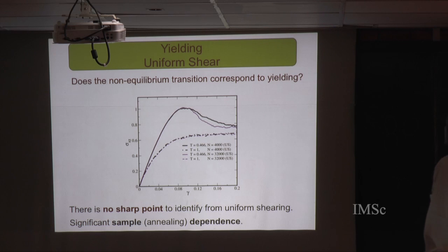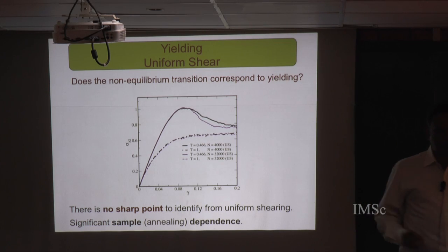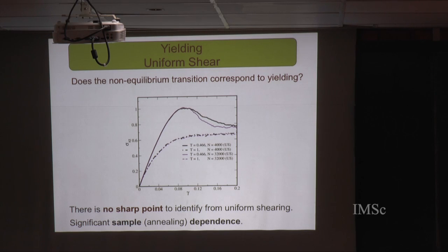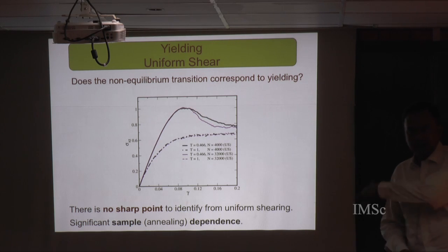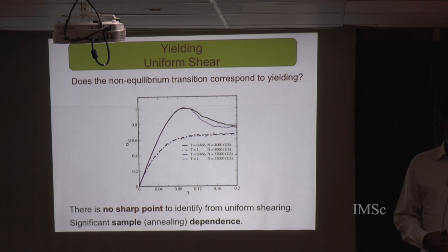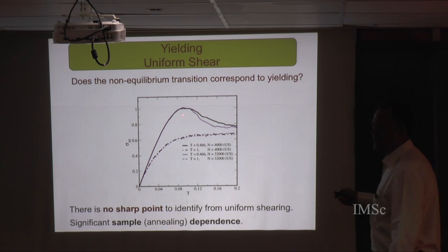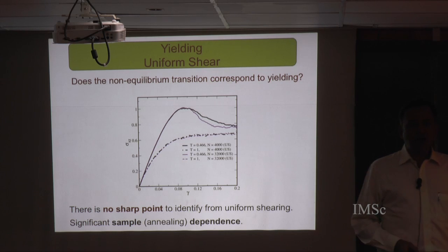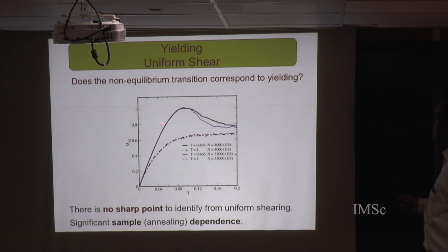And to answer that, we go back and look at how people normally characterize yielding. So here I have a stress-strain curve, and people say, if I look at a stress-strain curve that looks like this, which is the case for the low temperature or well-annealed glass, this stress overshoot and subsequent decrease in the maximum stress supported by the system is an indication of yielding or mechanical failure. And in this picture, you can't say exactly where that happens - it happens somewhere here.